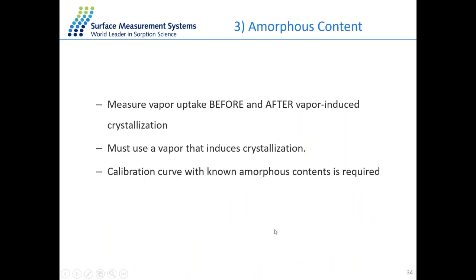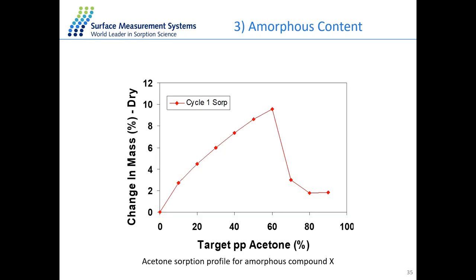In the next example, we're looking at amorphous content. This is understanding the amount of amorphous content you have in your sample. For this, we need a few things. First, we need to measure the uptake before and after the vapor-induced crystallization. So we must have a known vapor that does induce crystallization in your sample. Once we know this, we need a reference material. A calibration curve with known amorphous content is also required.